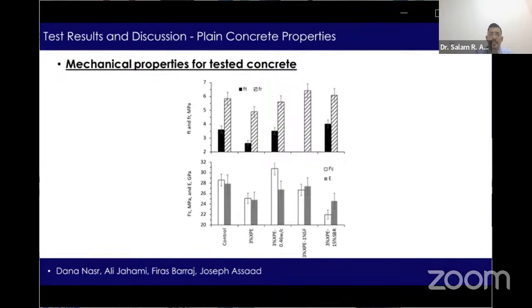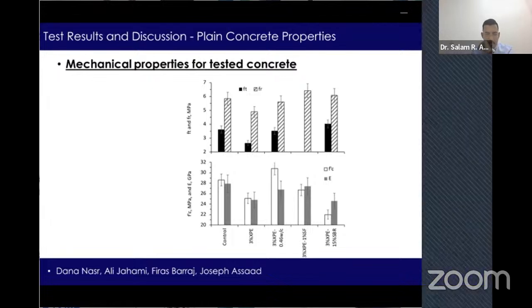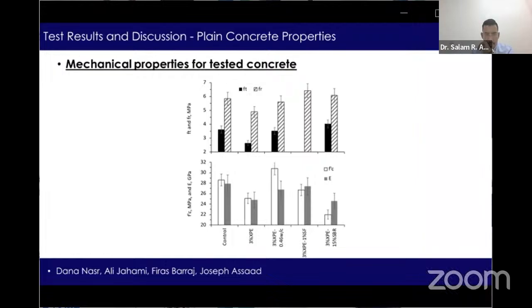The values that we have seen in the table are plotted in this figure that shows the mechanical properties, mainly the compressive strength and modulus of elasticity in the bottom figure, and ft, or splitting tensile strength, and flexural strength in the above figure for the different tested concrete mixes. It is very clear that the mechanical properties dropped with XPE additions due to their weak strength and lightweight characteristics if compared to natural aggregates. This drop in mechanical properties due to XPE additions was recovered, as previously seen, when the water to cement ratio dropped from 0.55 to 0.46. And for the last two mixes, as previously mentioned, the values of fr were recovered with the incorporation of steel fiber and SBR.